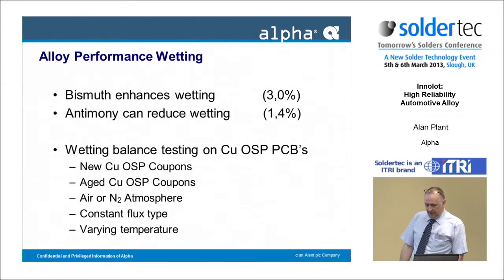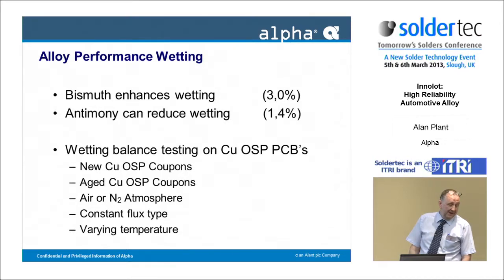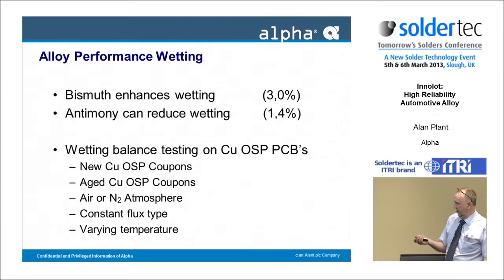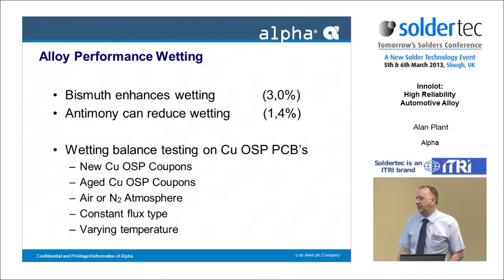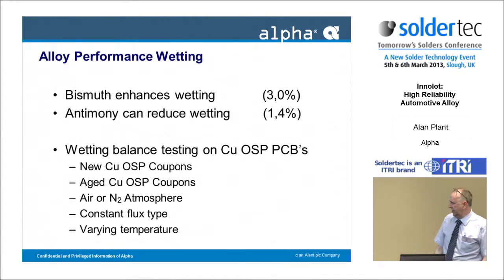Okay. So we've added these elements. What's it done to make the thing usable? As I say, in terms of wetting, bismuth enhances the wetting, antimony reduces it. So some tests were done, wetting balance tests on copper OSP. It was done on multiple materials. We tend to do a lot of our screening tests on copper OSP materials, especially from a solderability point of view, because normally that is the hardest to solder. It's often a starting point. It was tested on different atmospheres with a constant flux type.